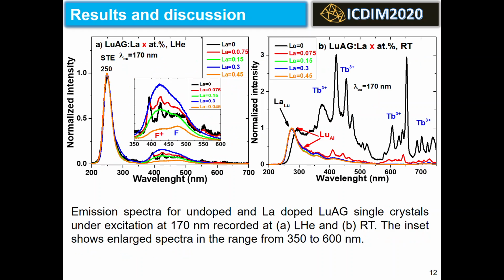These figures show liquid helium and room temperature photoluminescence spectra for undoped and lanthanum-doped LuAG single crystals excited at 170 nanometers. Spectra recorded at both temperatures show significantly distinct profiles. Namely, emission spectra recorded at liquid helium show three broad bands centered at 250, 415 and 475 nanometers.